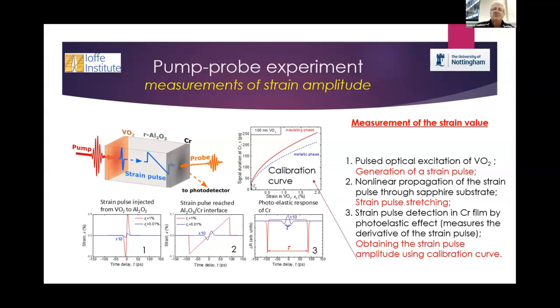So this is the experiment. We have a sapphire substrate, and then this VO2 film, a homogeneous film, made especially on this orientation of sapphire. We have a pump pulse, and by changing the intensity of this pulse we may control the amount of material undergoing the phase transition. Then we see that the strain pulse, in a similar way to what I showed with aluminum, is ejected and propagates through the substrate, and we detect it with the chromium film.